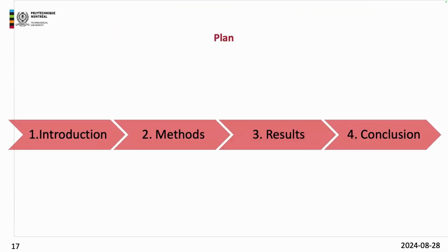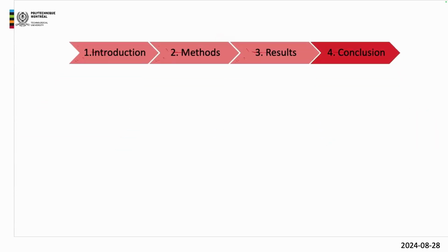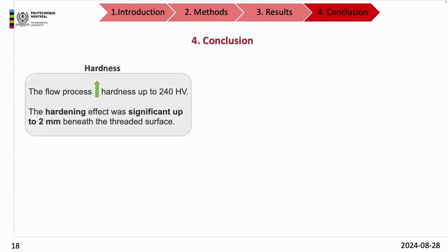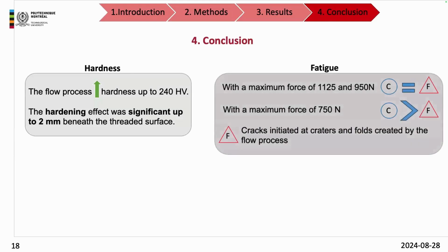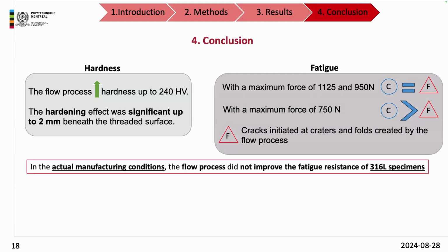So now let's conclude about this presentation. We've noted first that we have a positive effect, which is very nice for orthopedic implants, but we didn't find that this positive effect matched with the fatigue life results. So I can basically say that in the actual manufacturing conditions, the flow process did not improve the fatigue life of the orthopedic implants made from 316 stainless steel.